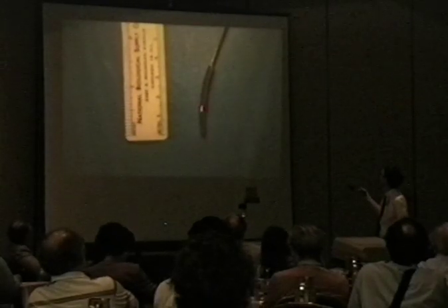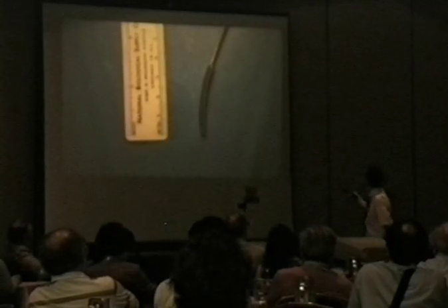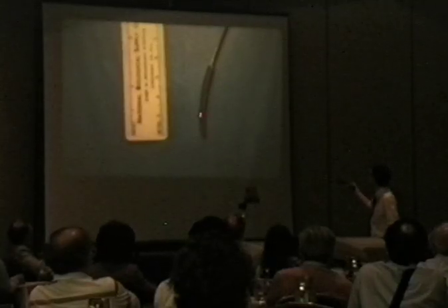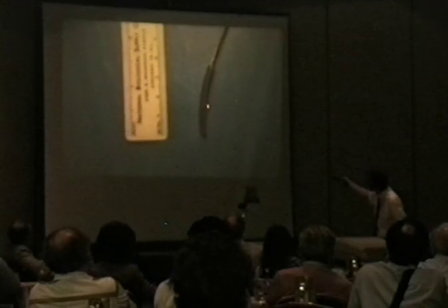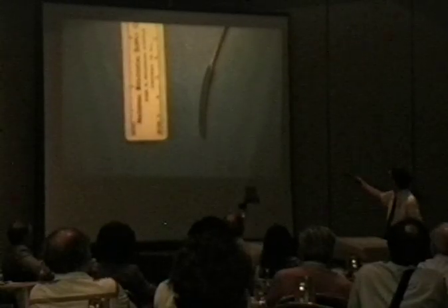So that's one way that I use in screening. Here is a piece of palladium that actually was cut from a piece of Engelhard. It was polished on one side, I'll tell you how, and the other side was just rough from the hacksaw blade. Notice that this has a greater radius of curvature. That means that it has larger volume expansion than the smooth side.